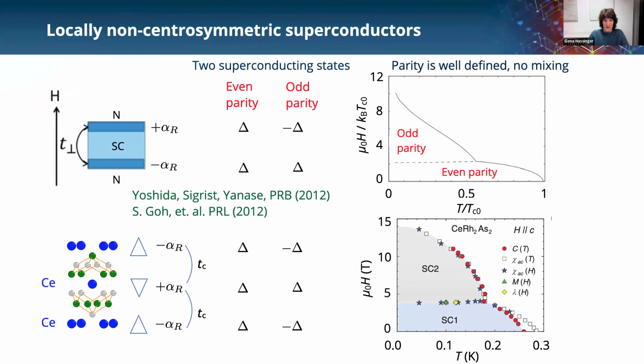And there have been a number of papers on a model system by Yanase and Sigrist and co-workers starting over 10 years ago, where they looked at systems where you have superconducting layers separated by normal layers. And this was inspired by experimental work by the Matsuda group, as for example in this paper, where they found very large critical fields. And so they considered that in the uppermost and lowermost layer of the superconductor, you break inversion symmetry locally, because here you have a different neighbor than here. And so you get a Rashba spin-orbit coupling term, which has an opposite sign between this layer and this layer. And then they also included some coupling between these layers.